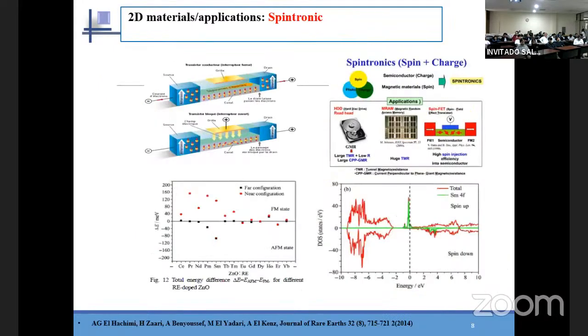The next example is spin. For this application, we exploit the spin and charge of electrons to get more storage of information, as we can use this material for magnetic memory or dynamic magnetic memory. We are looking for a magnetic material or semiconductor. As you can see here, this is zinc oxide with a rare earth material, and we found that in this case we have metallic behavior. Also, this material must have a ferromagnetic phase.